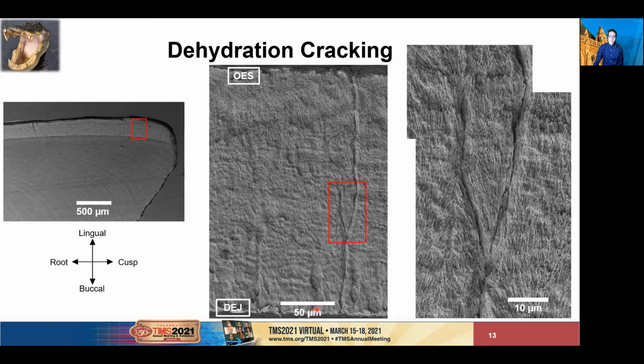The crack stays mostly straight with some slight deviations to accommodate for the kind of sinuous serrated interface between columnar units. The bifurcation itself seems to be initiated on a growth line, where a new layer of hydroxyapatite nanocrystals fan out from behind the previous layer. The crack paths then follow the same divergent trajectory as the crystals spread away from each other.